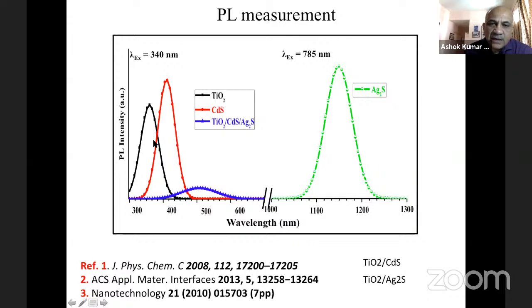So if you look at these black, red, and blue curves, the blue curve gives you the photoluminescence by the designed ternary nanostructured system, whereas for the pure titanium oxide, which is a UV semiconductor, and the pure cadmium sulfide, the luminescence intensity is much higher. And the reason that the luminescence has come down tells you that the lifetime of the charge carriers is high.